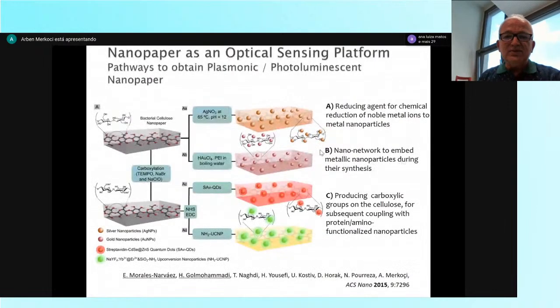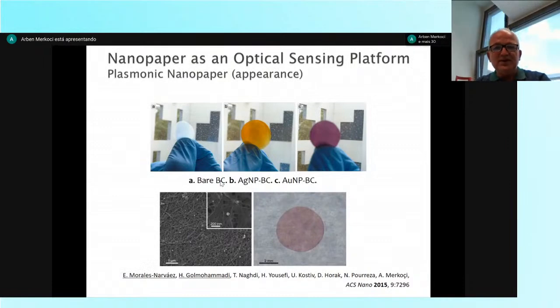So what we did is we tried to load this material with different kinds of nanoparticles, for example, silver, gold, but also quantum dots, up-converting quantum dots that can be used for different kinds of applications. In fact, we did it in different ways, either in situ production of these nanoparticles or ex situ, so produce these and then introduce them onto the paper. So once we have this nanopaper modified with nanoparticles, you can see these are also transparent. This is bare nanopaper in front of the windows of our institute. So you can see it is almost transparent. This one is with silver and this one with gold nanoparticles. And you can see, of course, the gold and silver nanoparticles inside the network of this nanopaper.